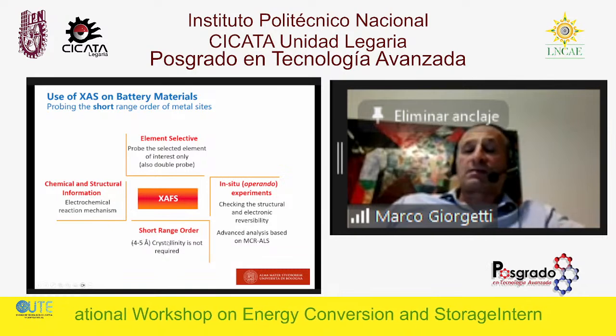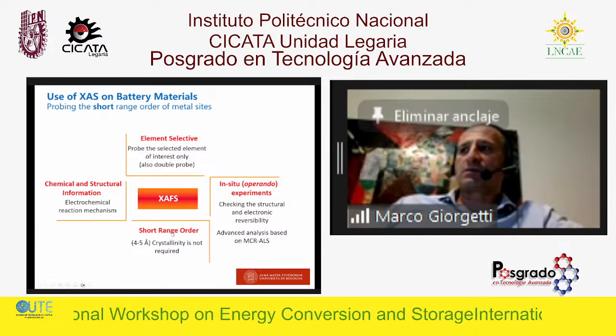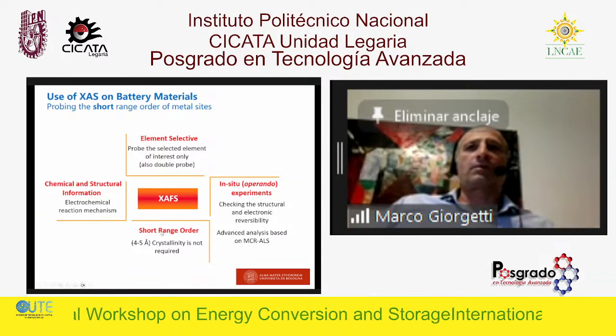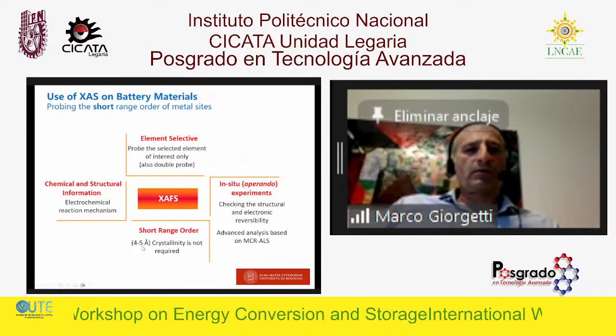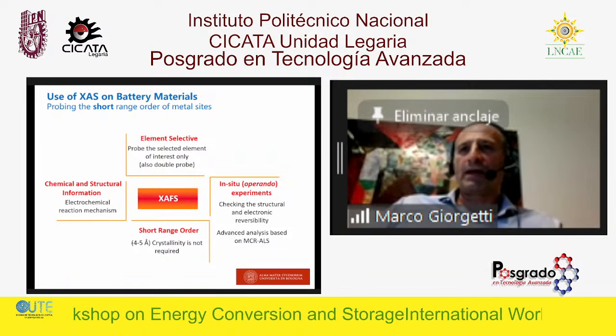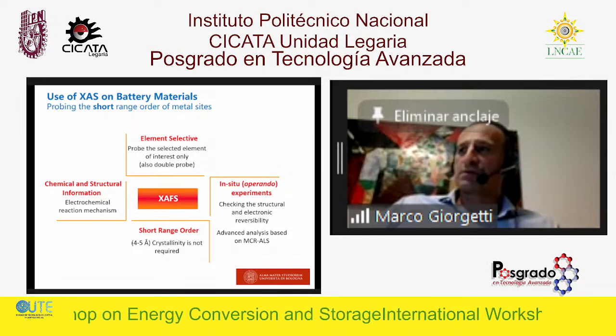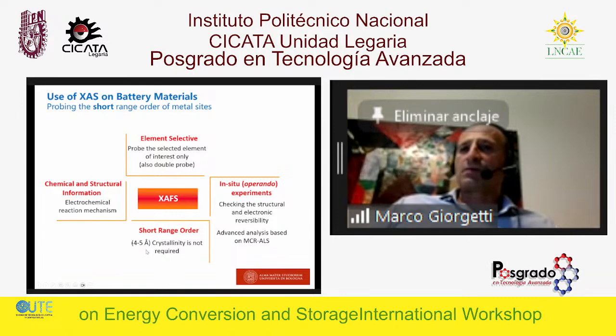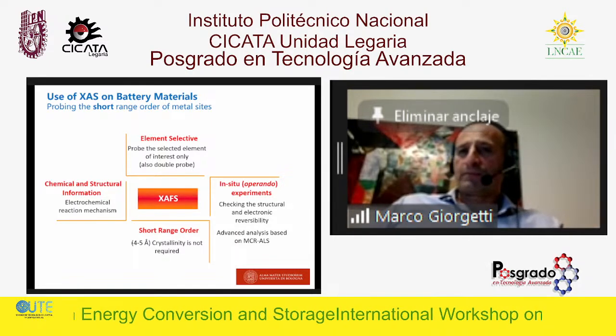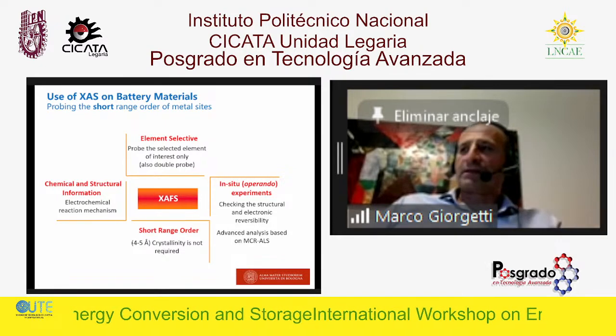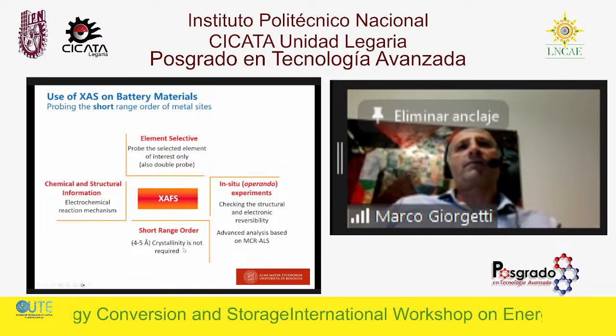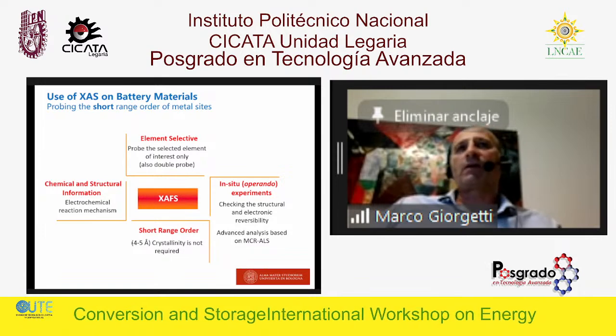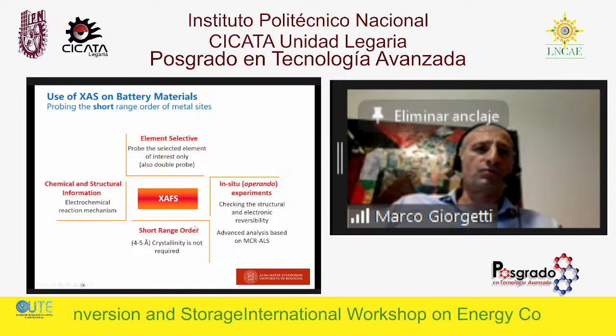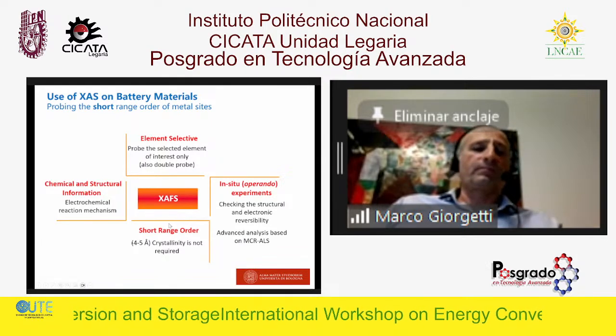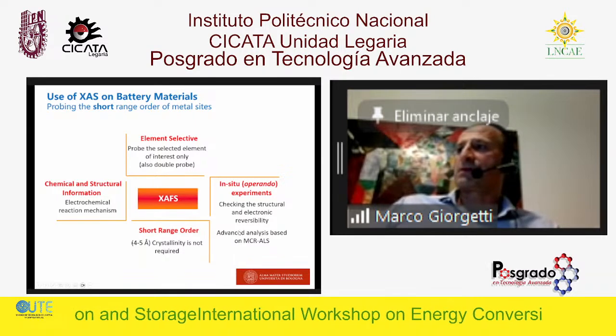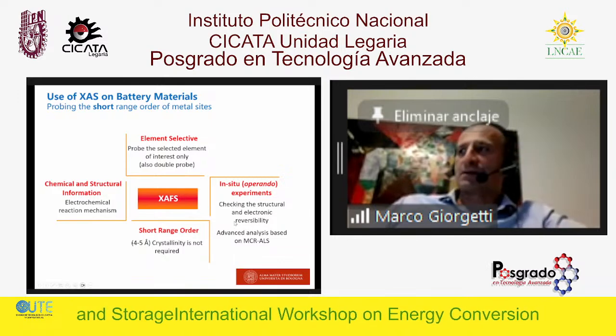It is short-range order, and this is something we have to keep well in mind, because we can probably see atoms at around 4 or 5 angstrom. In the case of metal hexacyanoferrates, this range is actually extended more than that, because of particular cases called focusing and super-focusing that allow very intense scattering from atoms that are just behind and in between. Another very important fact is that crystallinity is not required. As long as you have a battery material, of course, you start from a crystalline material and then we have a kind of amorphization. This technique is still suitable to check whether you have a structural or electronic modification upon charge and discharge of the batteries. We will also show some in situ and operando experiments as an example.